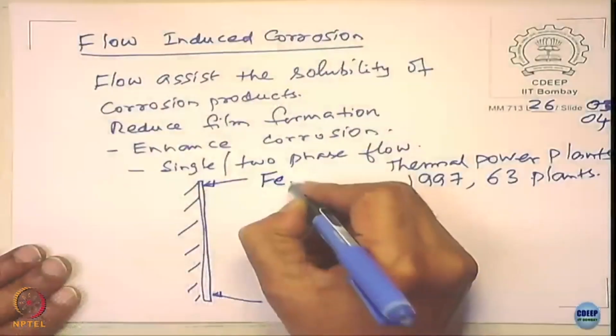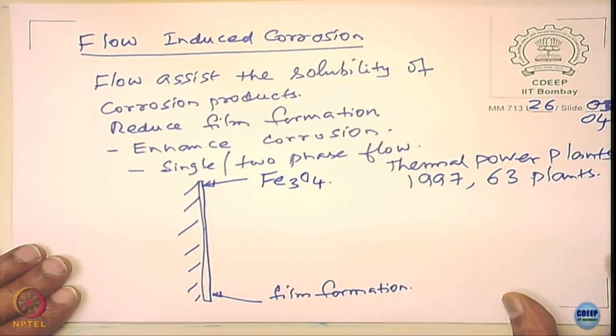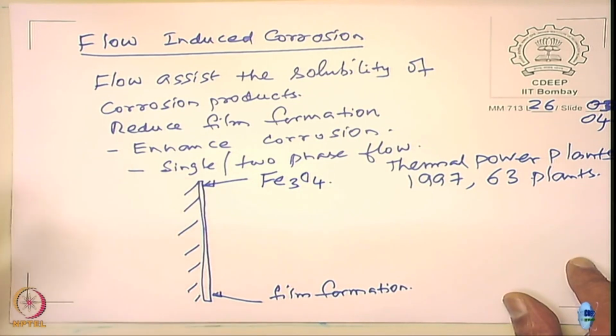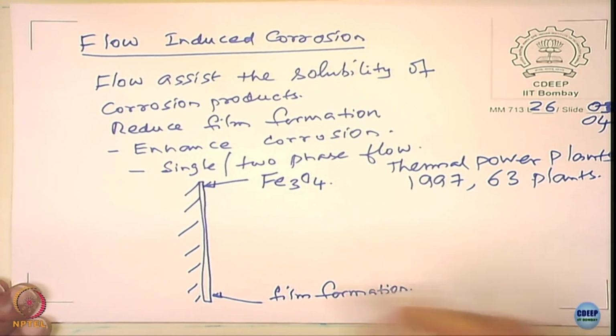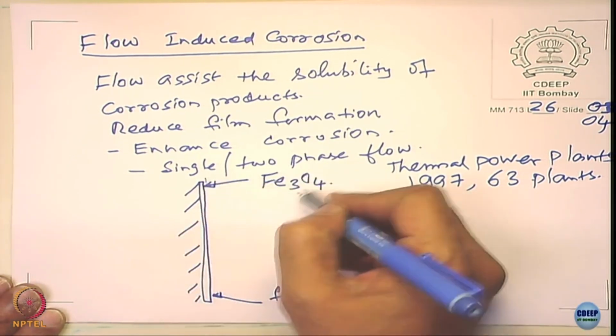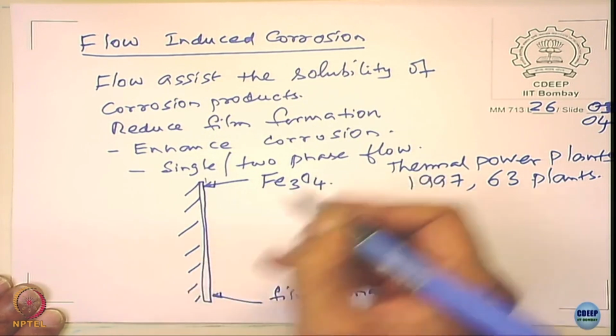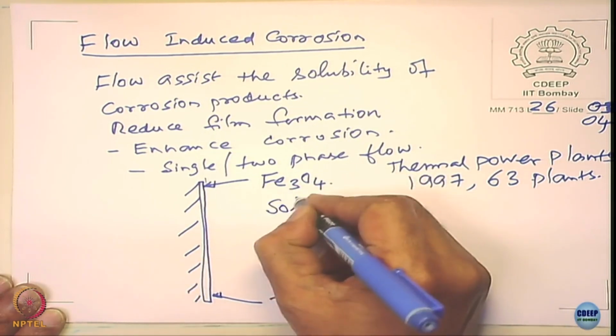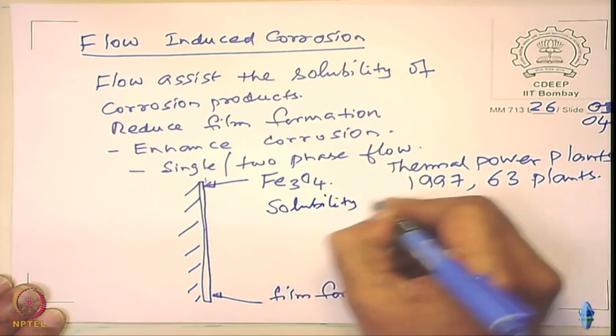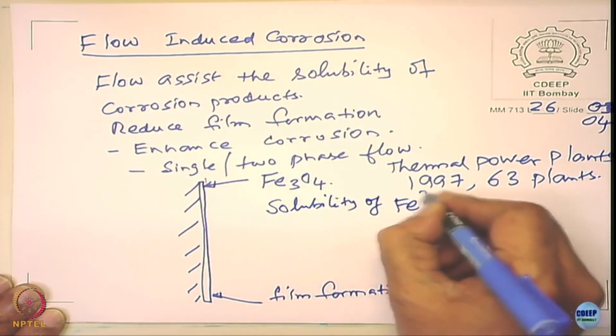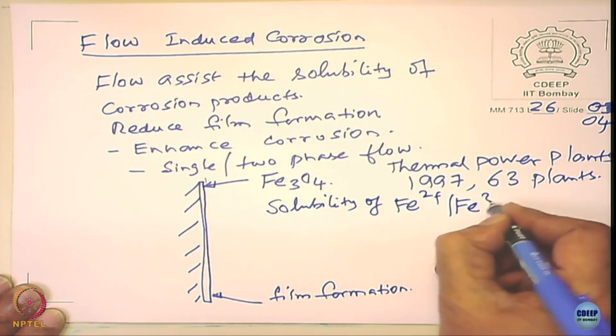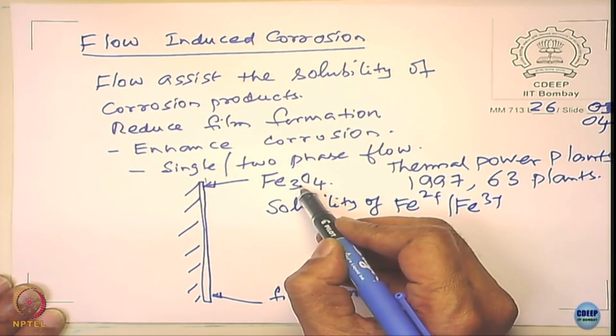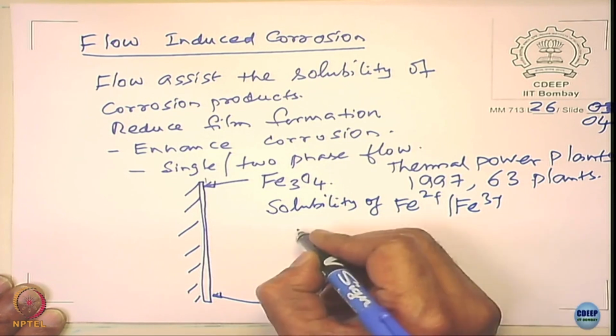So that means these oxides are generally a magnetic oxide, right. What is the magnetic oxide? Fe3O4 is a magnetic oxide formed, and this oxide prevents the corrosion of steel structures. Now please look at this formation. When does it form? This will form only when the solubility of Fe2+ and Fe3+, right. This constitutes Fe2+ and Fe3+, am I right? If the solubility of this one, okay,